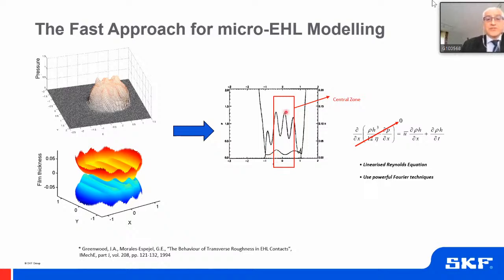For that, we focus our attention on the central zone of the contact. Now here, we have very high viscosities. And if we have very high viscosities, the Poiseuille flow term in the Reynolds equation tends to be small. So we can simplify this equation by just having a wave equation, a transport equation, which actually is linear. And if we know the solution for a sinusoidal, we can apply the powerful Fourier techniques to actually solve any topography that we want. Now, this is a very basic idea.